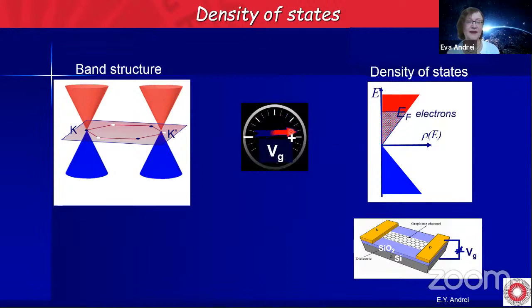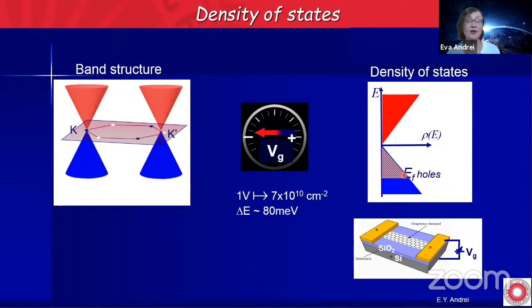Now, how does this happen? When I have a positive gate voltage, I'm moving my Fermi energy into the electron sector. A negative gate voltage moves my Fermi energy into the hole sector. Normally, if you have just a standard metal where the density of states is flat, it doesn't depend on energy. It's not zero at the band edge here. You can't put enough voltage in this capacitor to change the Fermi energy. You change the total charge, but the Fermi energy stays stuck, because it requires too many electrons to change it.